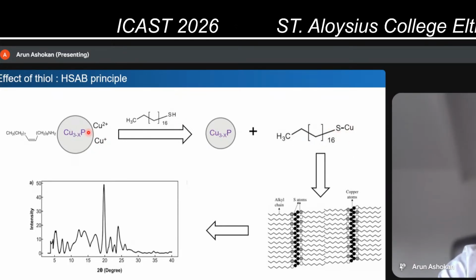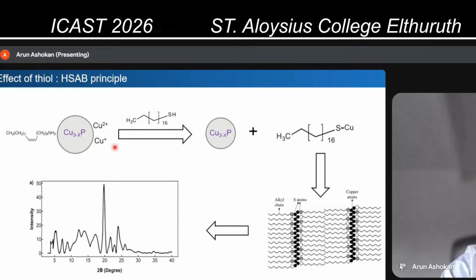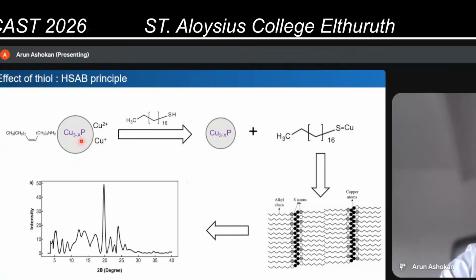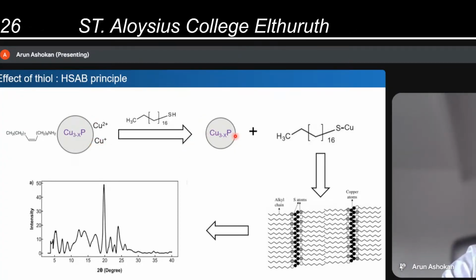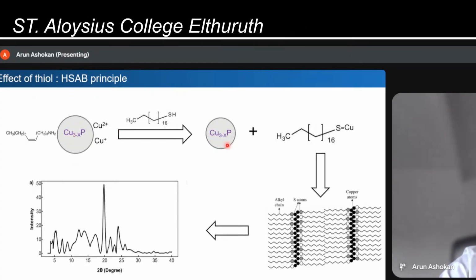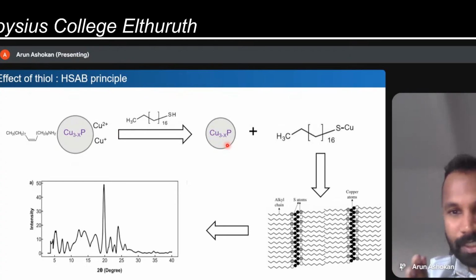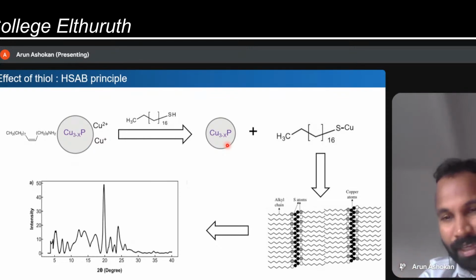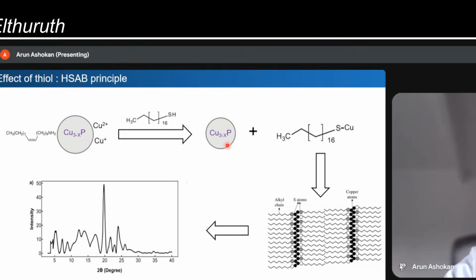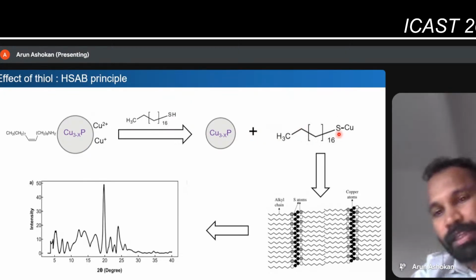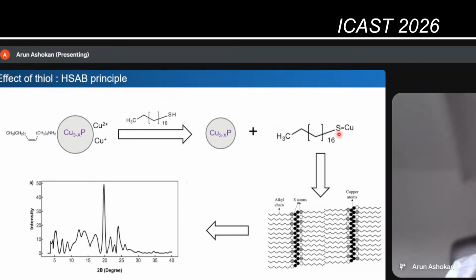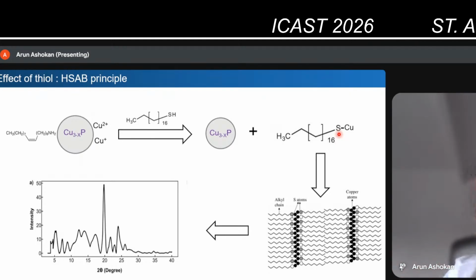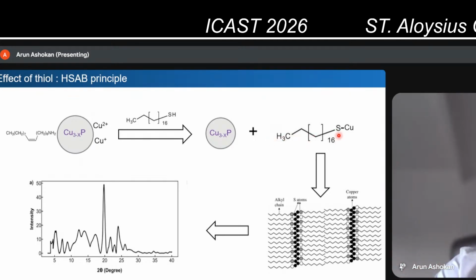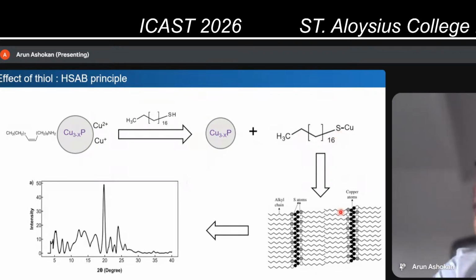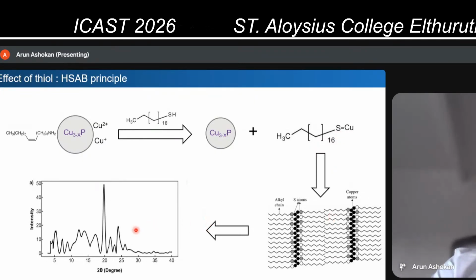So it will slowly start abstracting this copper plus from the nanocrystal. You have a lot of copper plus, so basically you will start etching the nanocrystal. The size of the nanocrystal slowly etches. That's why we progressively see a change in the color from black all the way to light brown yellow. And so you form this copper thiolate, and this copper thiolate appears as that white precipitate which I mentioned before. One of the interesting properties of this copper thiolate is that they form a layered structure, and you can easily detect them using XRD peaks.